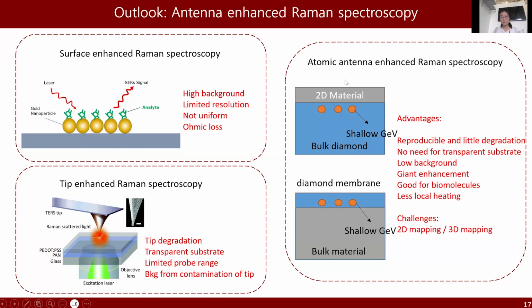So here we propose a new method for enhancing the Raman signal, which is called atomic antenna enhanced Raman spectroscopy. If we have a 2D material, we can put it on top of a bulk diamond and use shallow GeV to enhance the Raman signal. And if we have a bulk material, we can also put a diamond membrane on top.